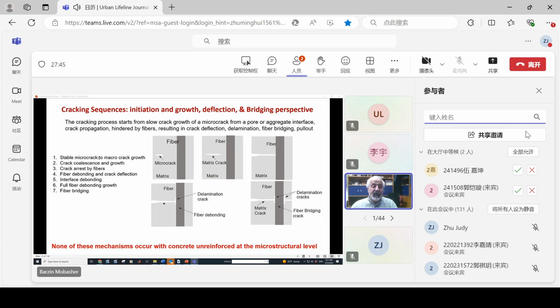Another way we can look at it is that if a microcrack grows large enough to hit a fiber, it gets diverted, it goes through a delamination crack, then the crack goes around. Now that delamination crack becomes a tunneling crack, which propagates up and down. This up and down means that now you have six crack tips that want the energy. So some of the items that I've written here, if you look at the slides later on, you can see these are all mechanisms that we can benefit from.